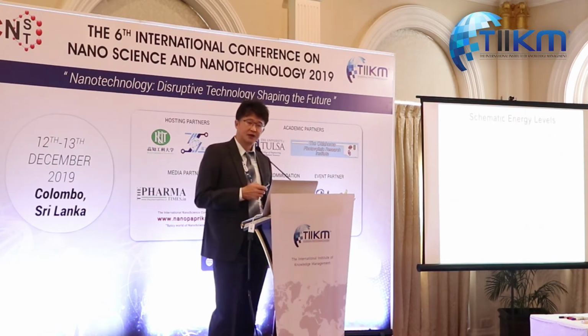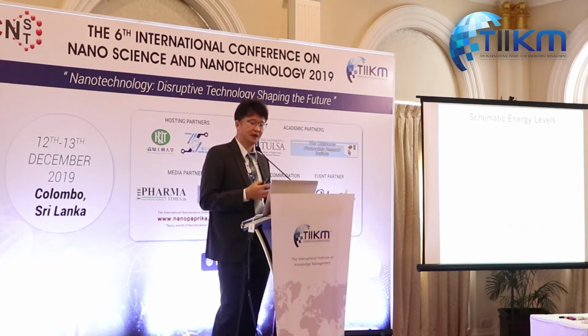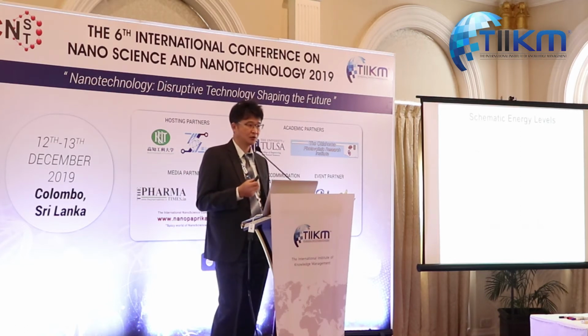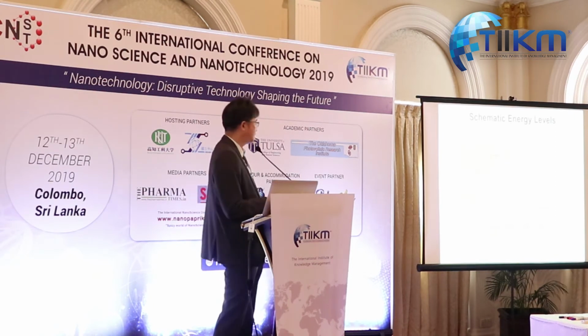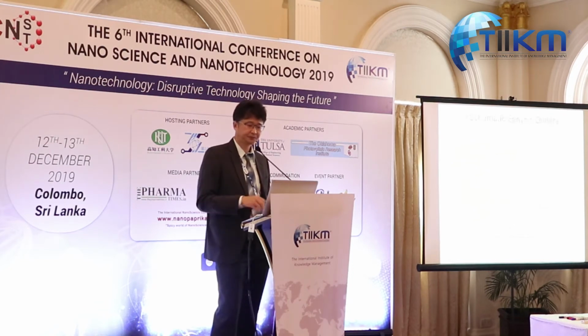So the lower efficiency for dimer YDD0 as compared to the reference is due to dye aggregation and also decreased LUMO energy level, which may impede electron injection to titanium dioxide. And the LUMOs for fused porphyrins are insufficient for effective electron injection to the titanium dioxide.